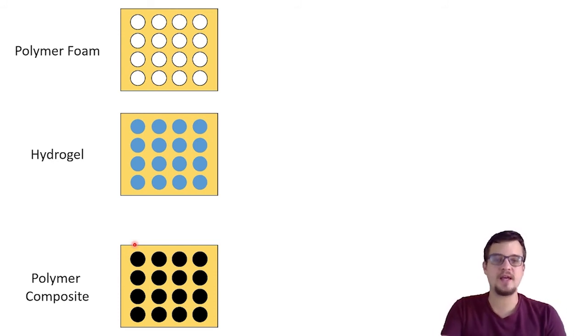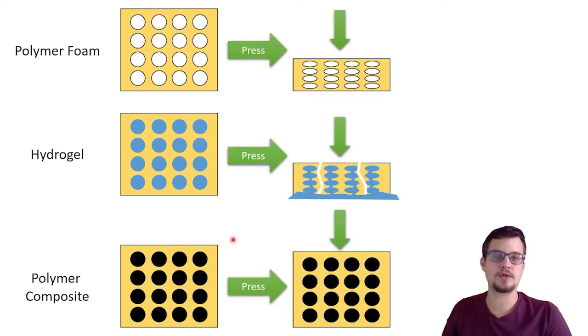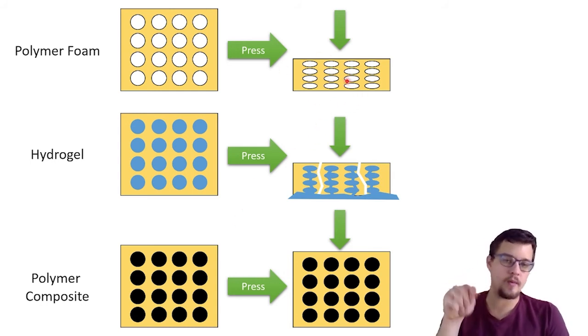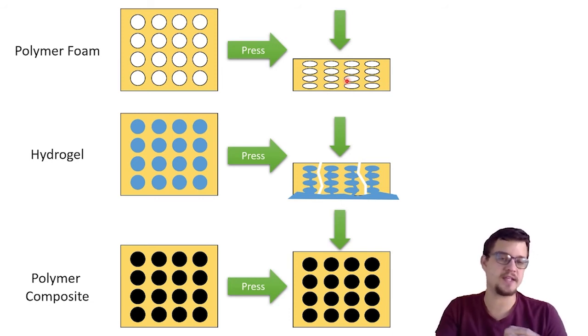Now, what's interesting is when we think about how these materials behave when we start to apply some stress, and you've seen some of this in the video. So if we think about having a block of each of these materials and we were to press onto those materials from the top, look at the different types of ways they react. So in our polymer foam, we know that we can squish that down really, really far because the air can come out of the pores. In our hydrogel, you saw that when I squeezed it, the water would come out, but also interestingly, it would actually start to fall apart and break apart. So think about if you've ever played with Orbeez. When you squeeze Orbeez, they tend to break up, don't they?